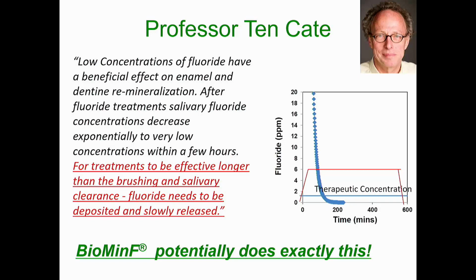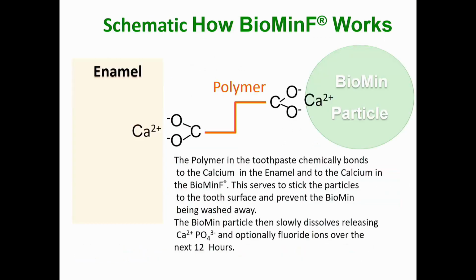And what Ten Cate said was for treatments to be effective longer than the brushing and salivary clearance, fluoride needs to be deposited and slowly released. And this is what we designed the Biomin F glass to do. What we want is a glass that doesn't result in high fluoride concentrations, but results in a continuous release of fluoride over 10 to 12 hours, the time period between brushing your teeth. And this is the red line on the graph on the right.